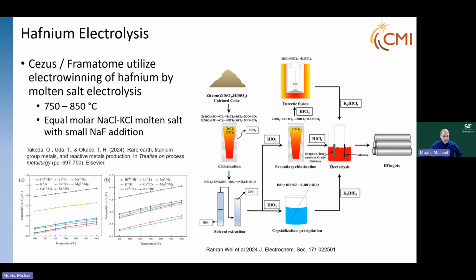In hafnium electrolysis, essentially the hafnium chloride goes into a molten salt of equimolar sodium chloride and potassium chloride. There's a little bit of sodium fluoride added, and that's to basically stabilize the hafnium ions in the molten salt, increase current efficiency, and prevent sublimation of the hafnium chloride. And basically, we go through a molten salt electrolysis where the hafnium crystals are grown on typically a graphite or inert electrode, and we have a graphite electrode on the other side.